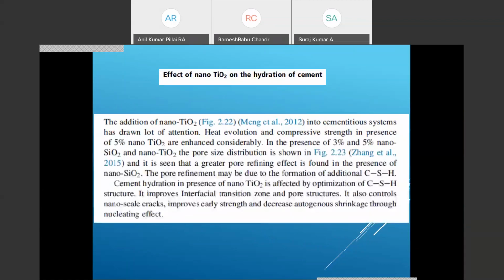Effect of titanium dioxide on the hydration of cement. The addition of nano into the system has drawn a lot of attention. Heat evolution and compressive strength in presence of 5% of nano titanium dioxide are enhanced considerably. In the presence of 3% and 5% of nano titanium dioxide, the pore size distribution is enhanced.